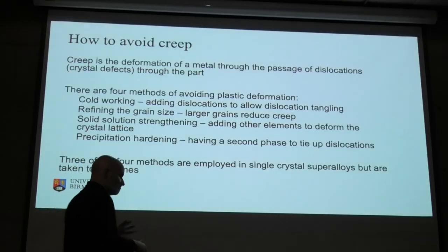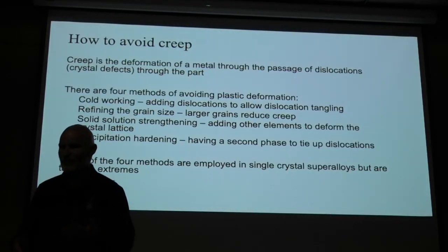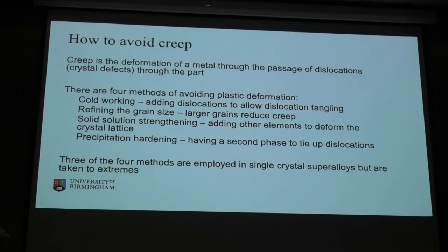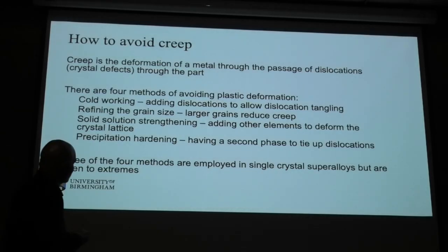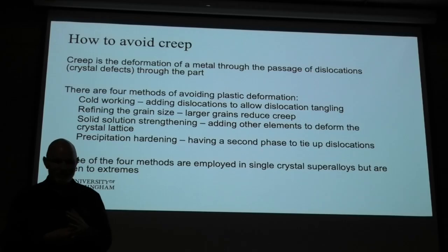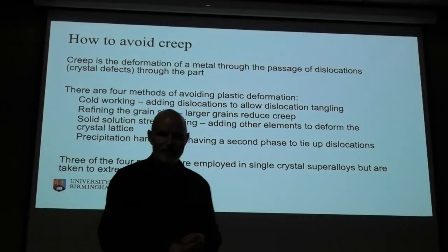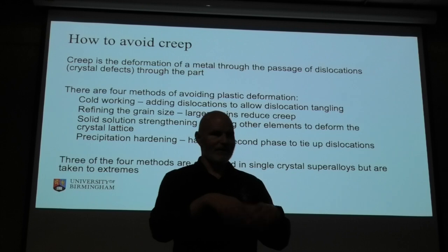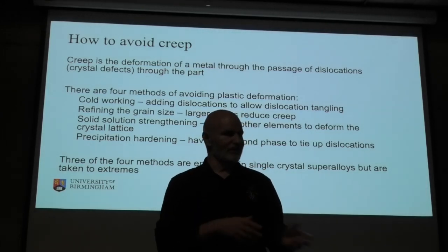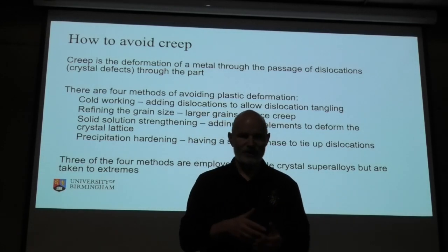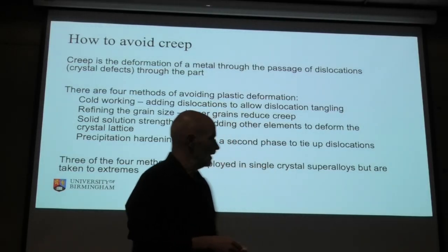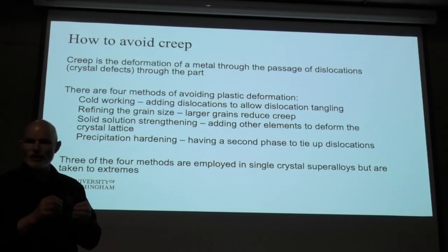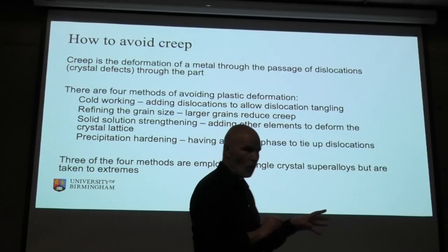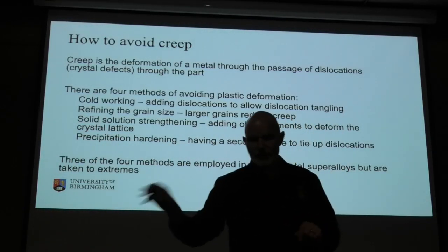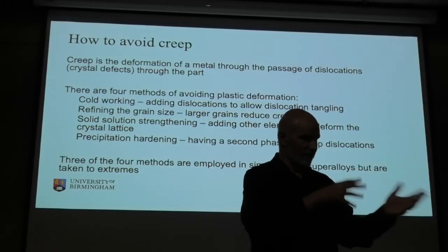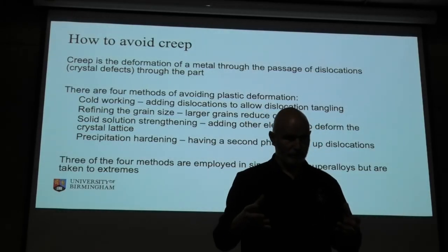Refining the grain size: larger grains mean less creep, because there are fewer grain boundaries - fairly simple. Solid solution strengthening is a favourite one - adding another element to deform the crystal lattice. You find an element you can stuff into your alloy that won't come out as a precipitate but just sits in solution, deforming the crystal, so dislocations - these atomic imperfections - meet it and get stuck. And there's precipitation hardening, where we try to get different phases to pop out of the metal when we heat treat it, at the right size to tie up these dislocations as they move around.